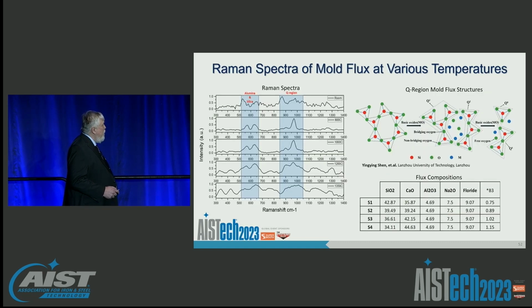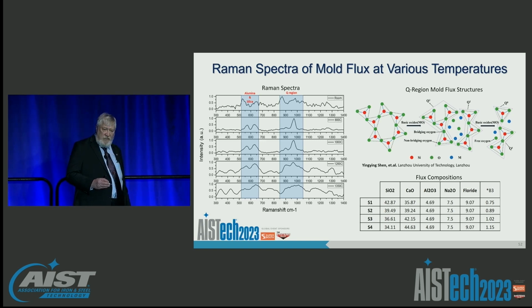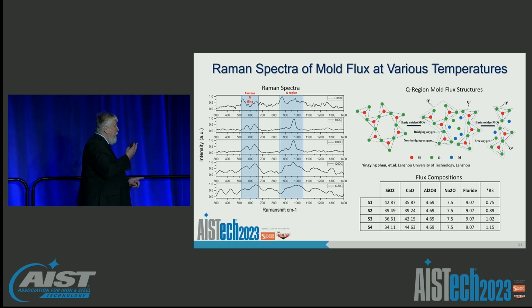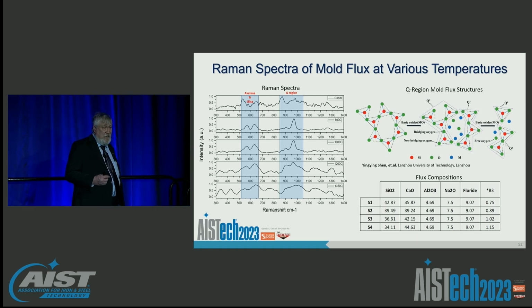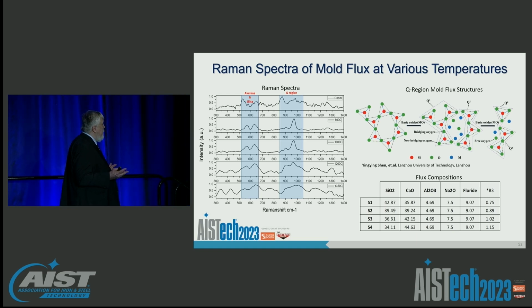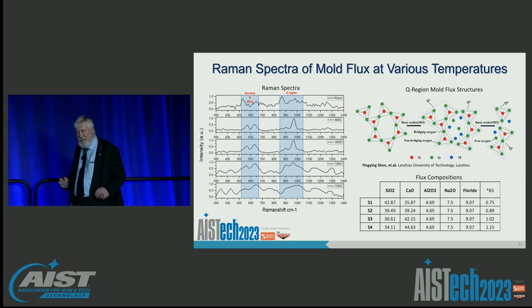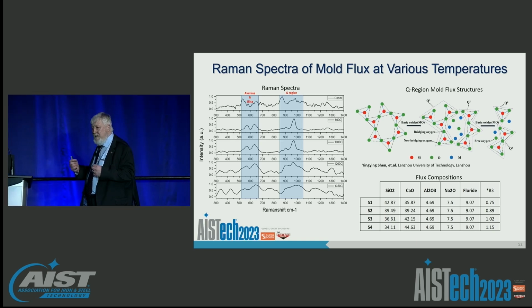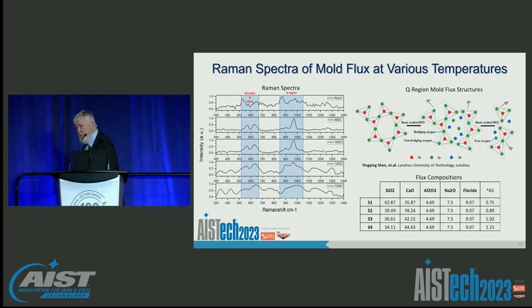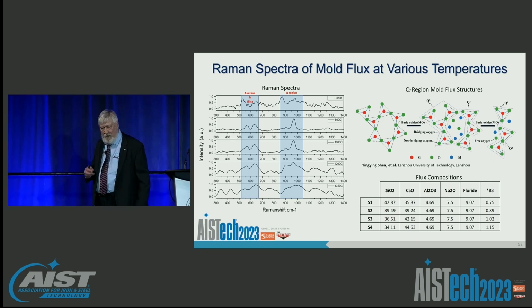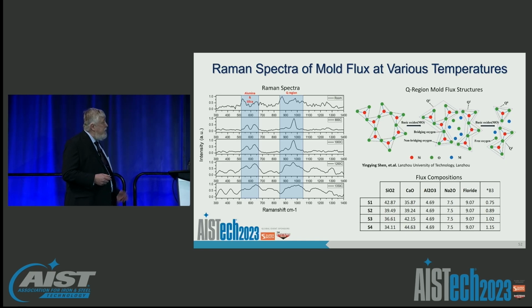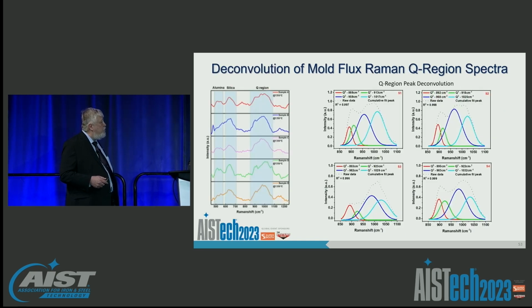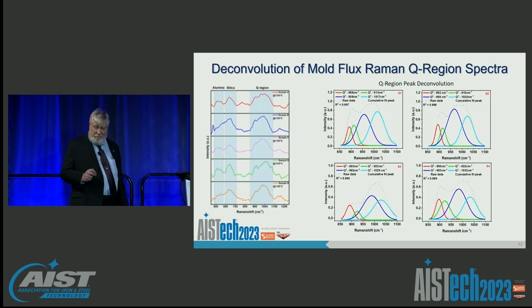And what we've been able to show is that we can not only collect that Raman spectra, but we can look at key regions of that spectra and correlate it directly to the slag structures. Turns out for silicate slag systems and flux systems, the so-called Q region, which represents the polymerization state of silicate chains in the slag, can actually be detected by their Raman signature. Each one has a unique frequency. And we can take the Raman spectra and deconvolute that spectra in order to extract the fundamental components.